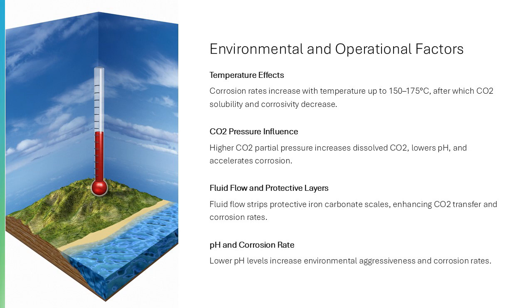pH levels directly influence the aggressiveness of the environment, with lower pH correlating to higher corrosion rates. Under certain conditions, protective FeCO3 scales can form, significantly reducing corrosion if they remain stable. Additionally, chemical inhibitors are commonly used to create protective films on metal surfaces, mitigating corrosion. Understanding these factors allows engineers to predict corrosion behavior and implement targeted control measures to maintain system integrity.